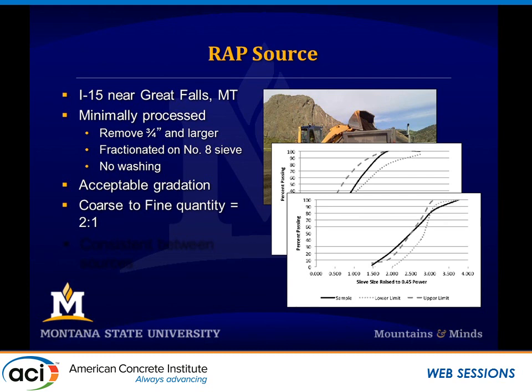Another important aspect, it yielded about twice as much coarse as fines doing this. So we had, by weight, about twice as much coarse aggregate as fine aggregate. And then this was consistent between RAP sources. So we tried a bunch of different RAP sources from around the state and determined that these gradation curves were about the same when we applied this process. So that was our RAP source.